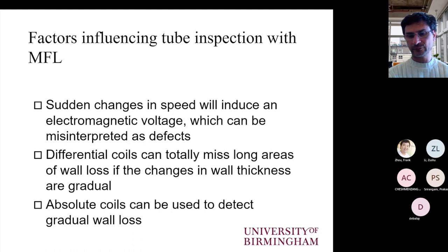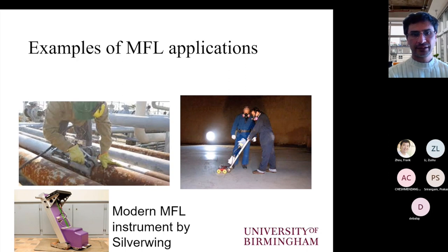Typically, what we can do with the differential coils is identify the ends of general corrosion, so where it starts and where it finishes, because that's the point where the value instantaneously would change. So with differential coils, we can find the ends, but we typically miss the in-between level of wall loss. And that's why the absolute coil is required as well. These are some examples of magnetic flux leakage.